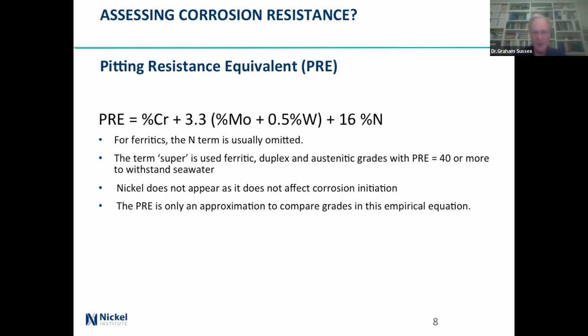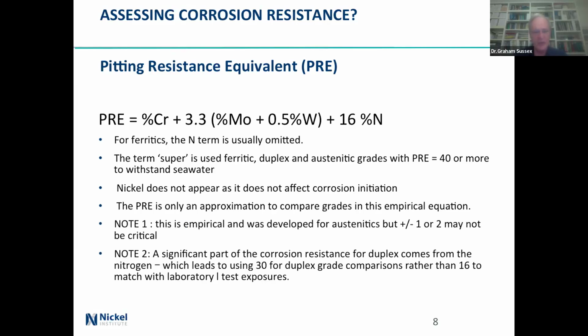There's nickel not in there. I've lost count of the number of times people say the nickel isn't good enough, therefore we're going to have bad corrosion resistance. It's not true. It simply selects what happens in terms of what the microstructure is. And this is a formula that was worked out for austenitics. It does work for ferritics. It does work for duplex, but it's only an approximation. And so if you get a variation of 1 or 2, then it may well not be critical, but it does work, as I say, for ferritics.